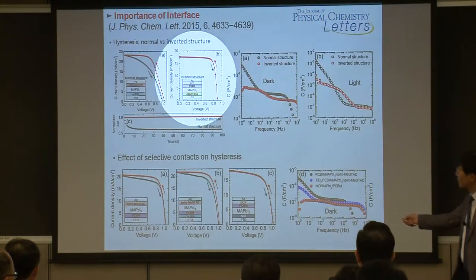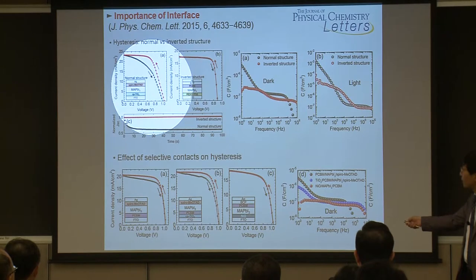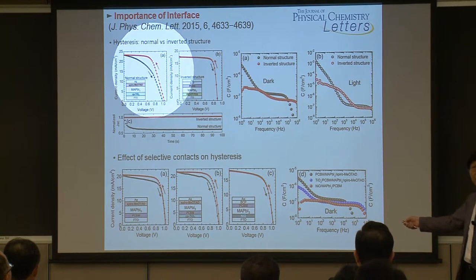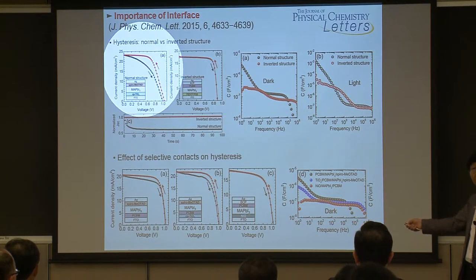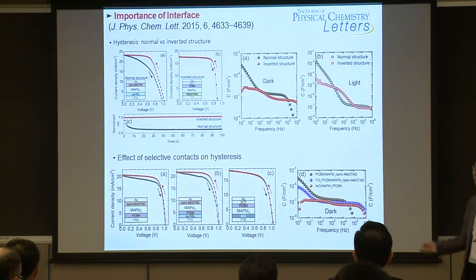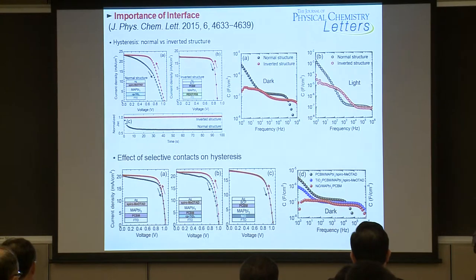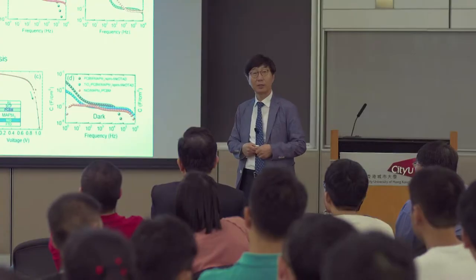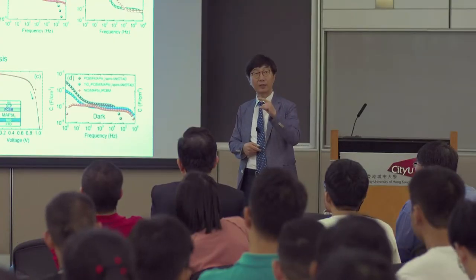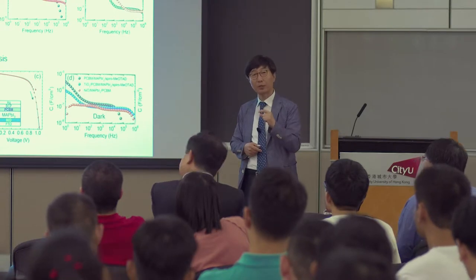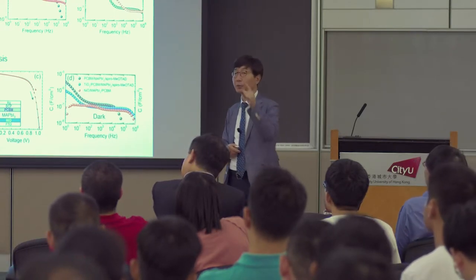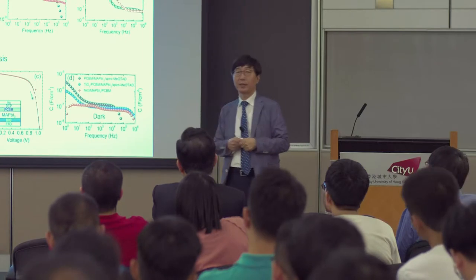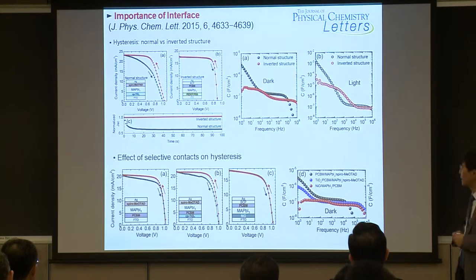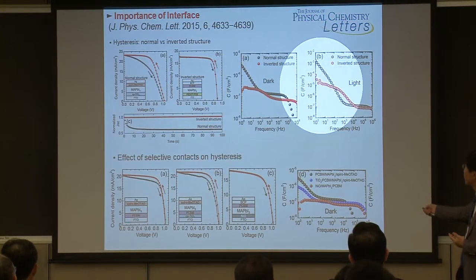But even using the same methyl ammonium lead iodide perovskite material, the normal structure shows a severe IV hysteresis. But the inverted structure, you cannot see any IV hysteresis. The question is probably the interface, selective contact material, or the perovskite near the interface may affect the IV hysteresis or may affect the capacitance here.